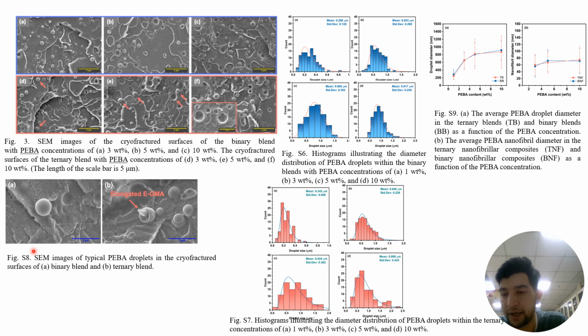In the compatibilized blend, the drop size of the minor component is influenced by interfacial tension and viscosity. The addition of a compatibilizer typically reduces the interfacial tension, resulting in smaller droplets. However, if the compatibilizer contains reactive groups like the epoxide ring which react with the minor component, it can increase the viscosity ratio and lead to larger droplets.